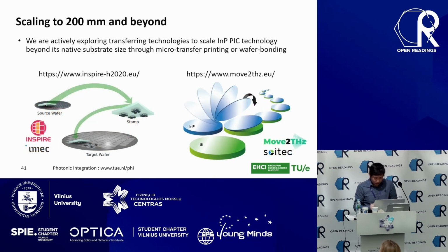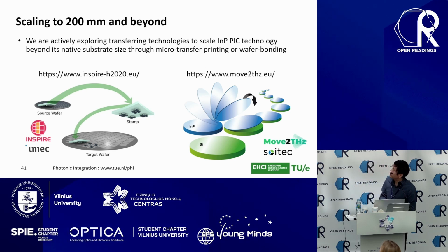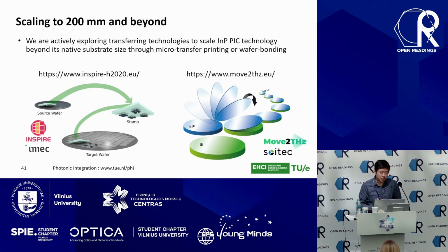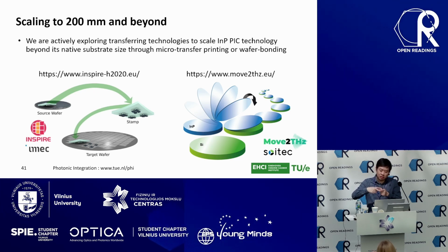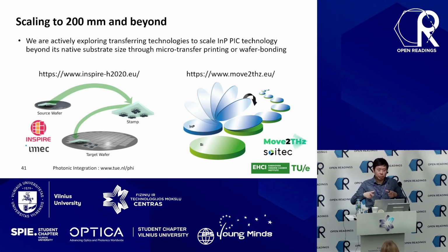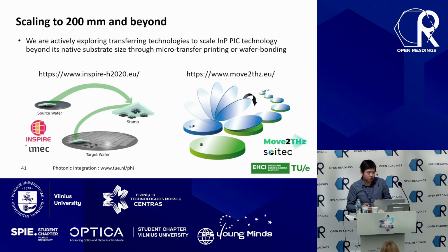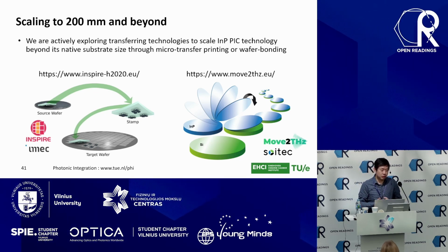We are also, last thing but not least, thinking about scaling of wafer size, because we are always asked by people, hey, indium phosphide, what's the future for indium phosphide? Indium phosphide, most of the labs do 2 to 3 inch, and we are slightly better at 4 inch. Industry just moved to 6, but that's about it. 6 inch might be the fundamental limit for the indium phosphide material system, just because of the brittleness of the material itself.